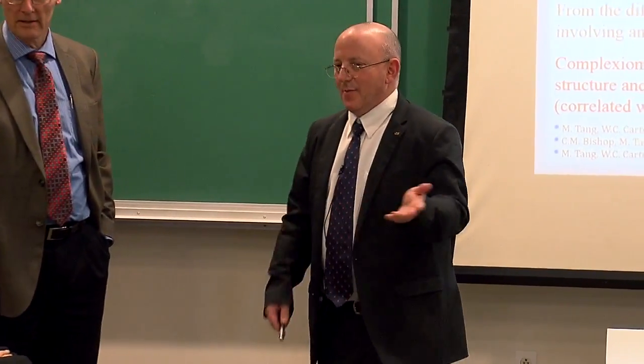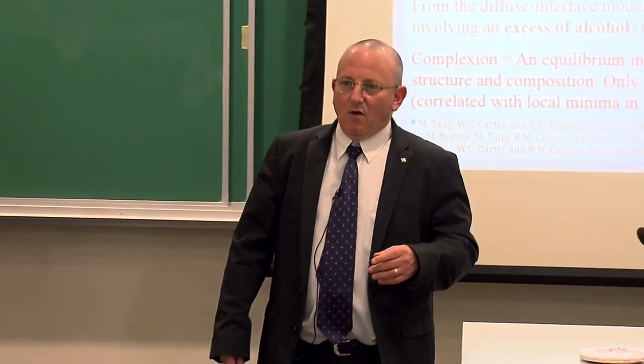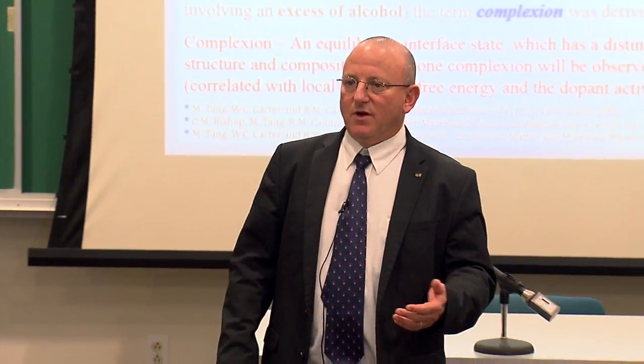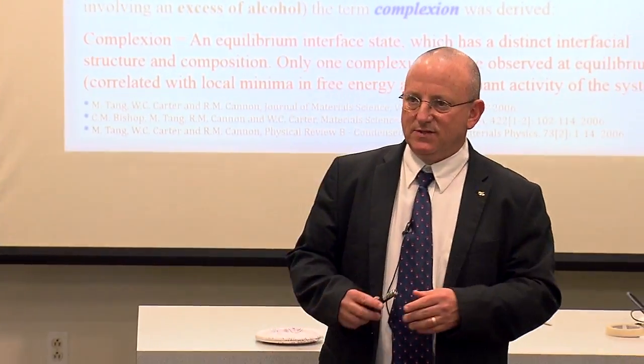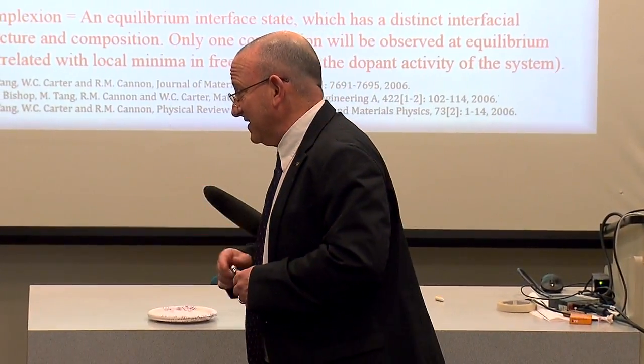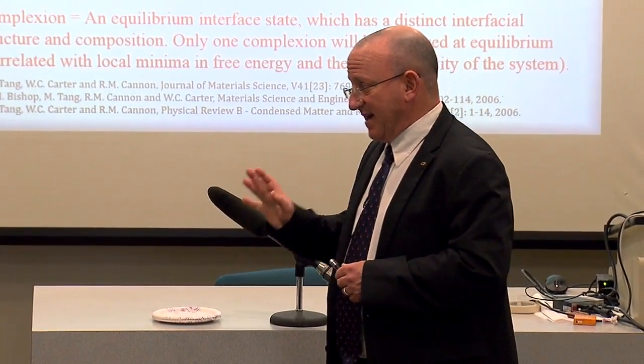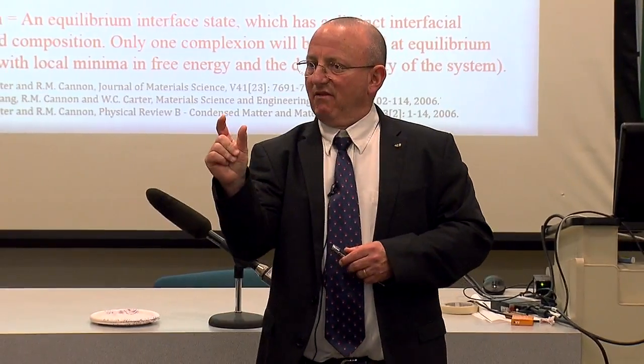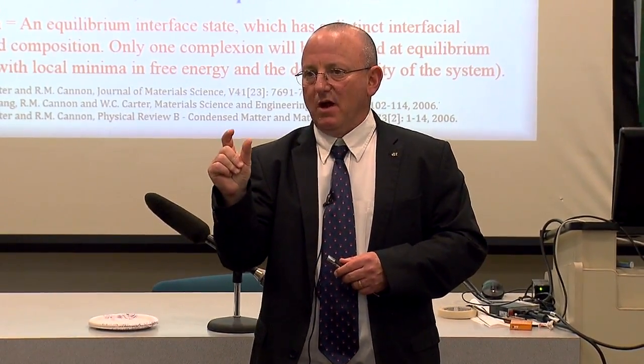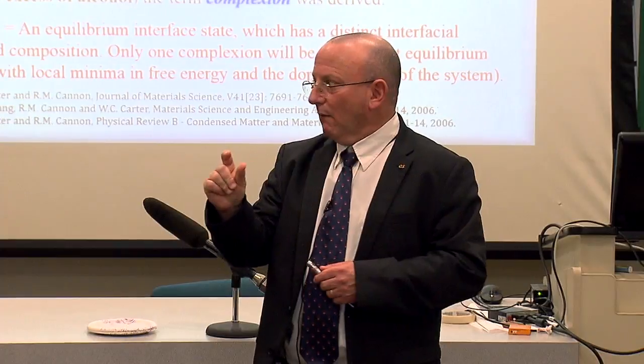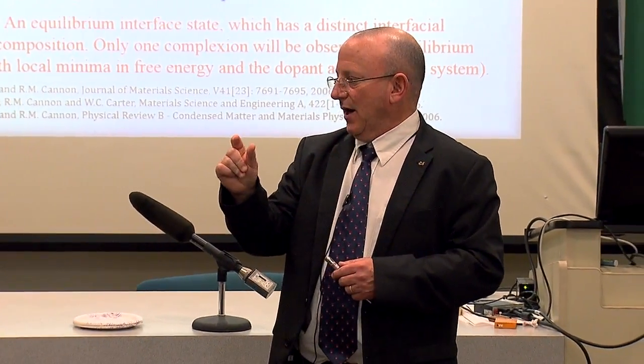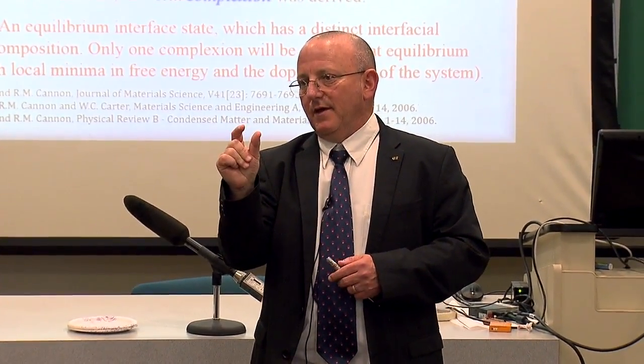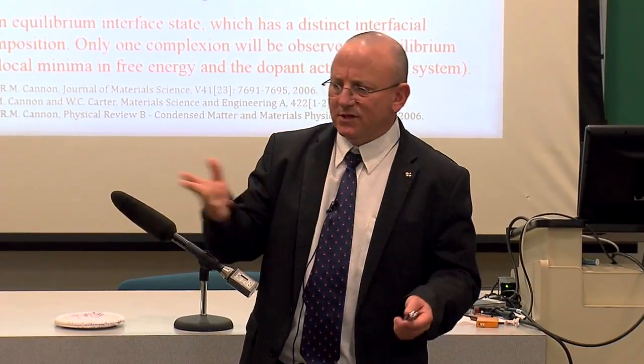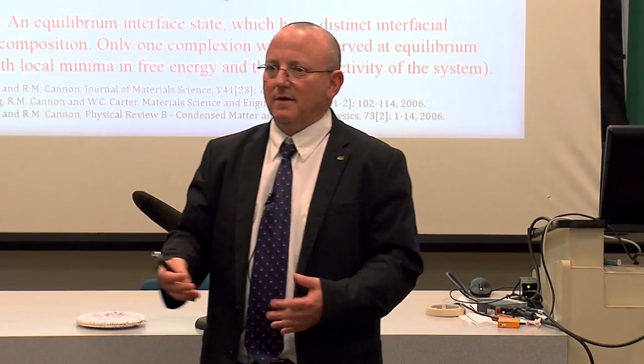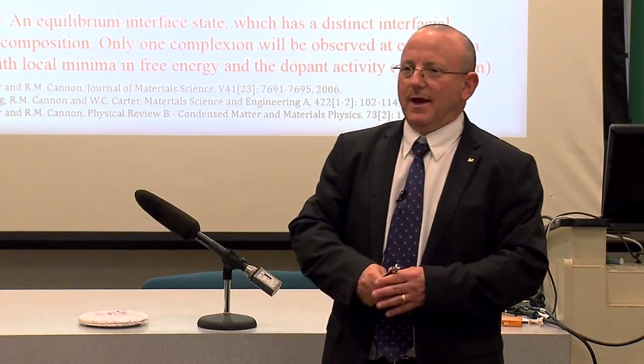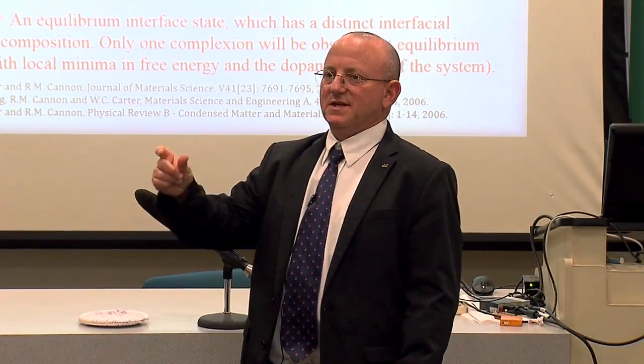So I have to give the background. There was this oversimplification of the concept of these transitions, based not on chemical analysis, and they actually didn't even know how much they had in solution, but on the width of the state of a grain boundary measured by STEM, which is iffy at best. And there was an attempt by a group, by the way, it was a legitimate attempt to simplify things and make it stomachable or edible, and they tried to simplify this into six states.